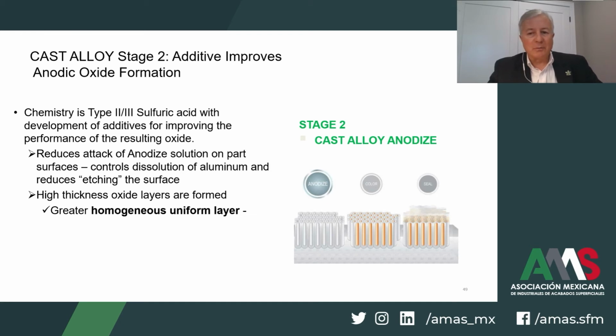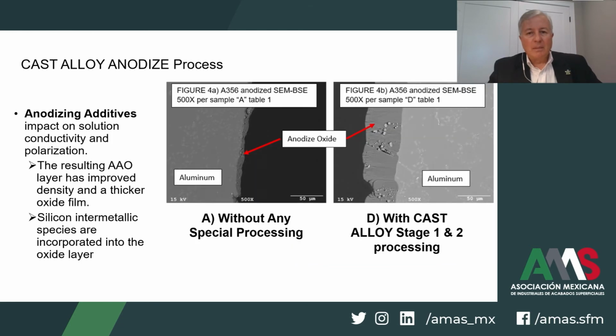The additive system helps to control the aluminum dissolution, and it minimizes the attack, which is very critical to avoid complex smut formation during the formation of the oxide anodic layer. As shown in this slide in the two photomicrographs at the same magnification, there is a much different oxide thickness and formation of the anodic oxide layer comparing the use of a cast alloy stages 1 and 2 compared to traditional processing in attempts to anodize the surface.